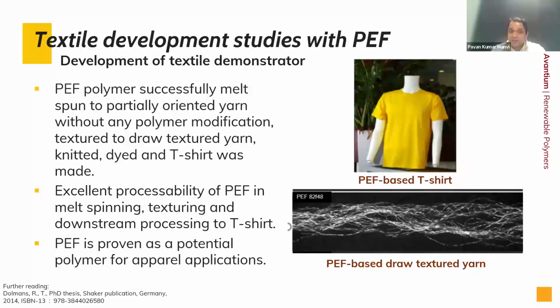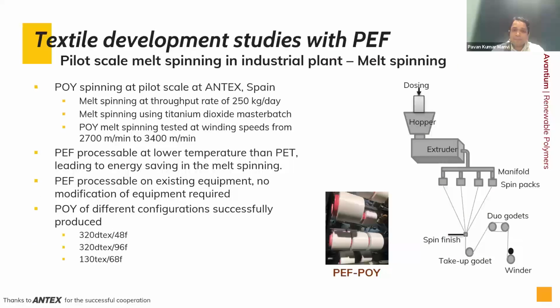And it is already a dyed yarn or dyed fabric. Therefore, the dyeability has also already been proven. Then, after all these basic studies, we started industrial scale development, and here we took the industrial scale process as a benchmark. PET spinning takes place between 2,700 and 3,400 meters per minute. So around 3,000 meters per minute is a standard process, which we developed for PEF.